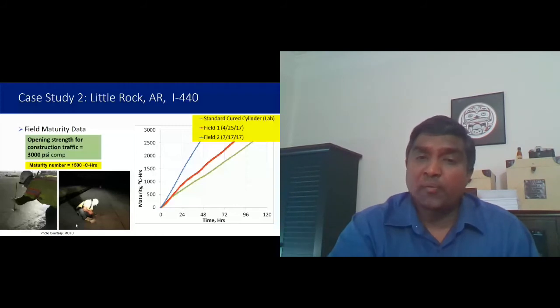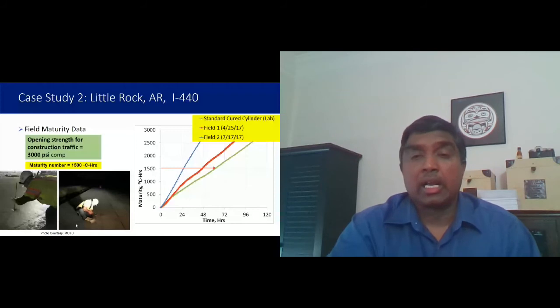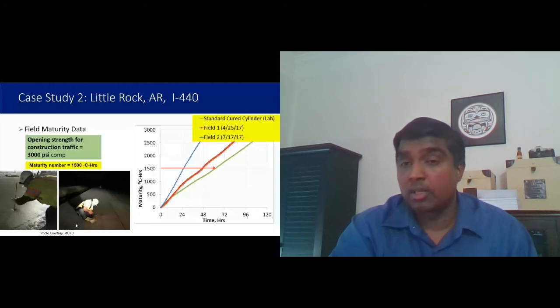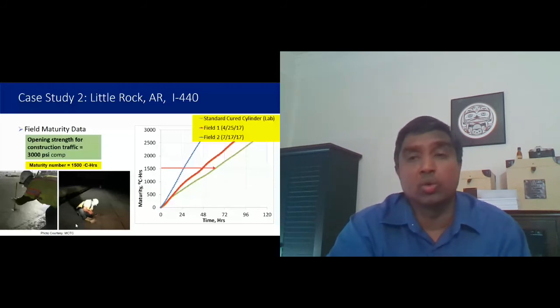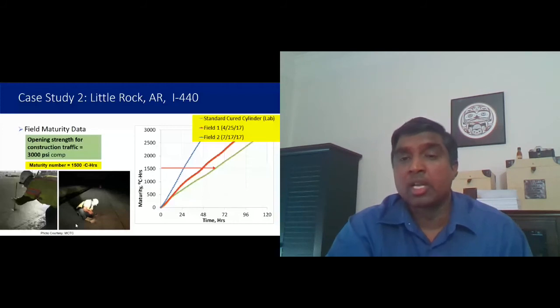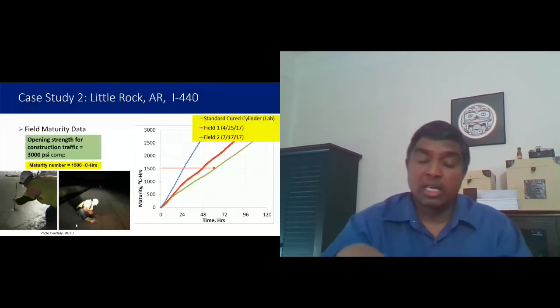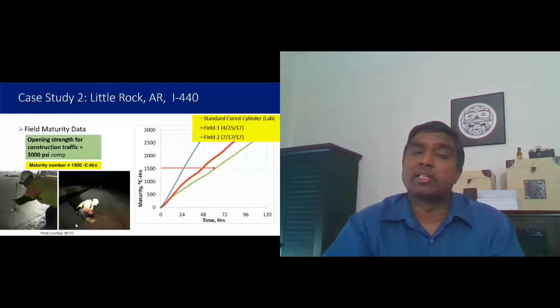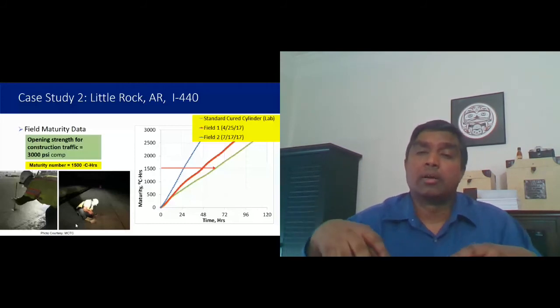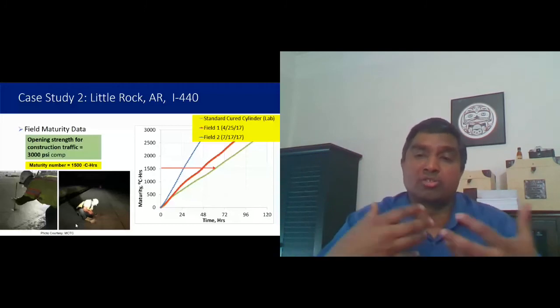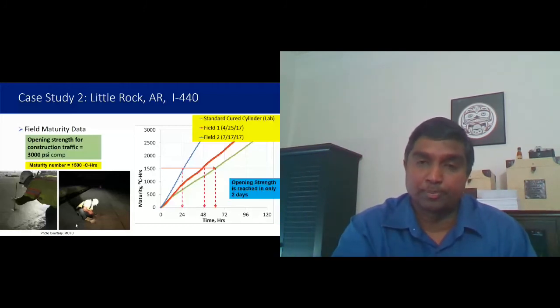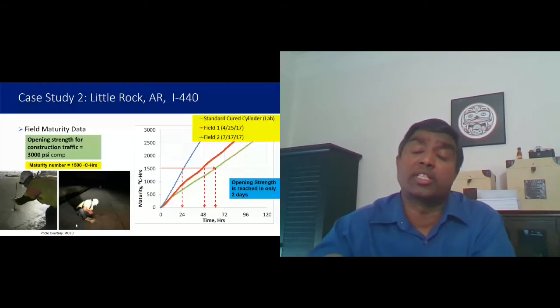So for 1500 degrees C hours for the mix in Arkansas, in summer it only took a day to reach 3000 psi. In spring it took 2 days, versus more than 2 days for the standard cured cylinder. So again, as you could see, with maturity, the cool thing is it's also considering the impact of weather on strength gain, like we've talked about all along. So it's not like it will always give you one number.